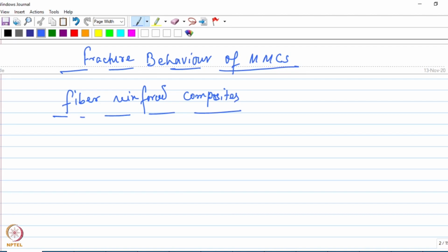So when you talk about the fracture behavior of a fiber reinforced composite which is loaded in a particular direction, let's say in the direction parallel to the fibers, then you need to also consider how the matrix behaves as it is loaded in the presence of the fibers. So you need to consider the matrix properties as well, particularly the ductility. Because the material flow in the matrix will be decided by the ductility. I mean, how far it can go through the plastic deformation and accommodate it. That is what the ductility talks about, right? So for a ductile matrix, the ultimate strength of the composite material is relatively insensitive to the matrix behavior. That is the first point to note.